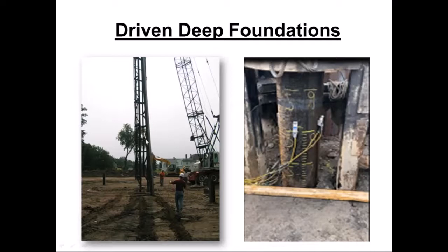So the photo on the left, this is an H pile that's being lifted up into the leads, and up top here is a big diesel hammer. This project had a big diesel hammer. So once the pile is put at its location, then the hammer is going to drive that pile into the ground to a specified depth and a specified capacity. So the capacity is determined during field testing.